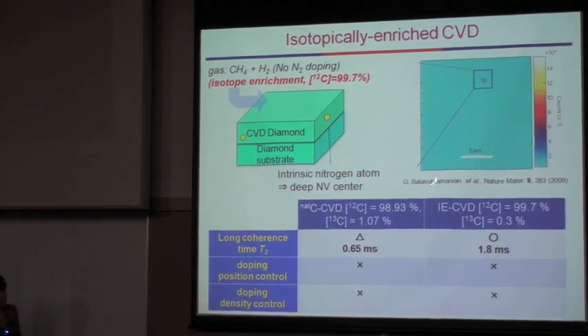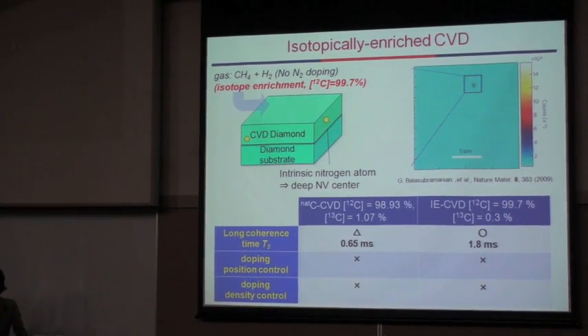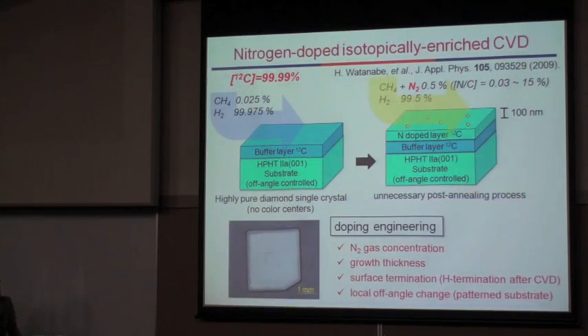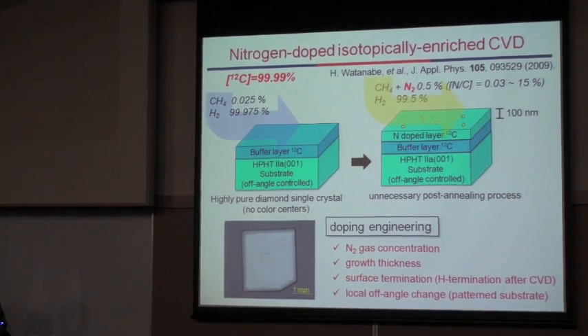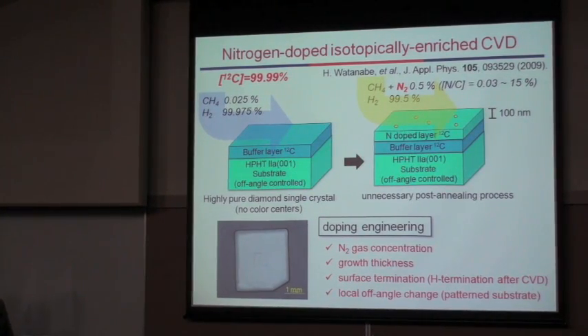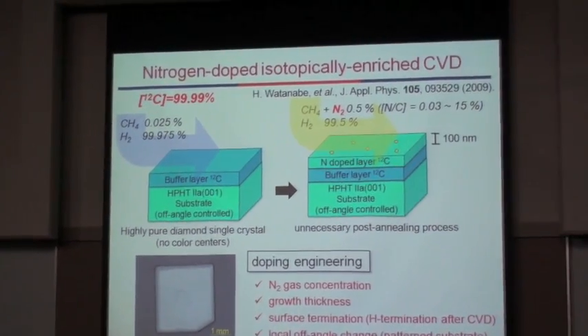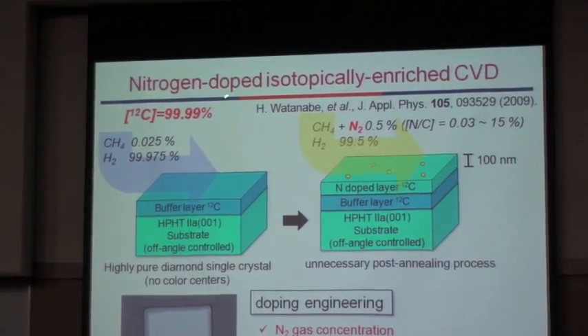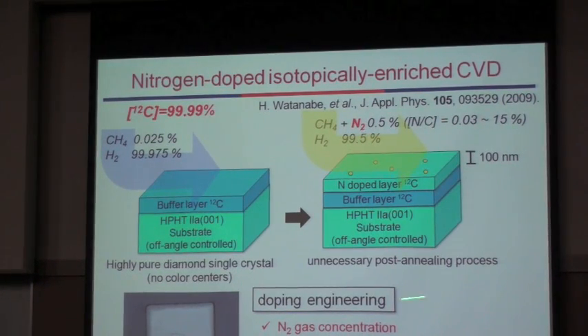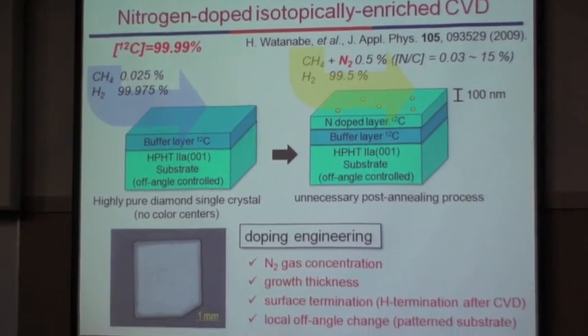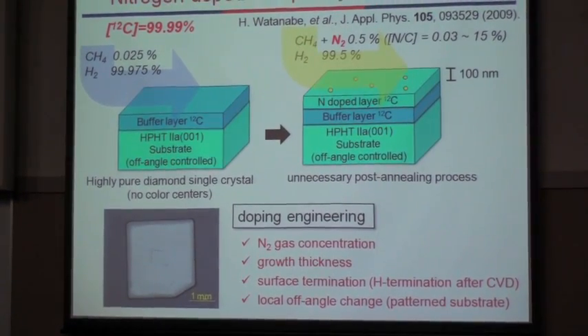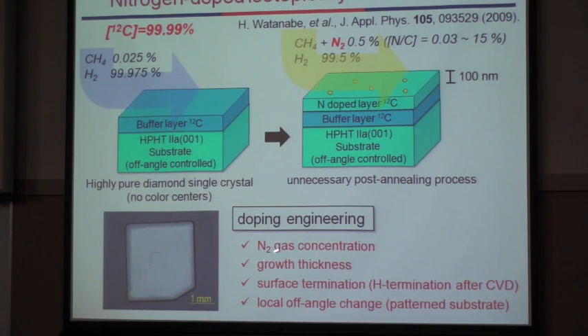However, in this technique, the doping control is difficult. So we developed this isotopically enriched CVD by doping nitrogen during the CVD process. By doping nitrogen gas, we can control the doping position and doping density by changing the nitrogen gas concentration, growth thickness, surface termination, and local off-angle.